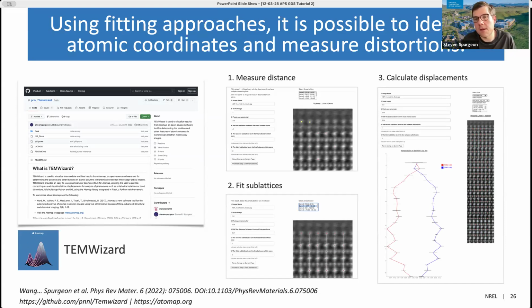So this is not really sophisticated. It's not necessarily even machine learning. It's just a 2D Gaussian fitting of the atomic positions. But what it allows us to do is to move from raw data to now a distribution of coordinates. Once we have this distribution of coordinates, we can calculate many, many parameters of the material. In this case, we're particularly interested in displacements between the two different sublattices.